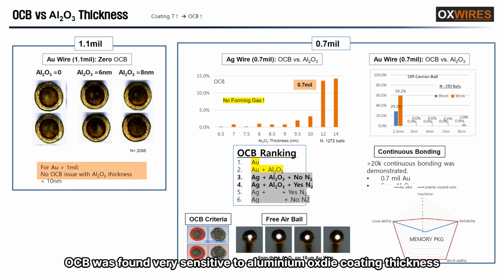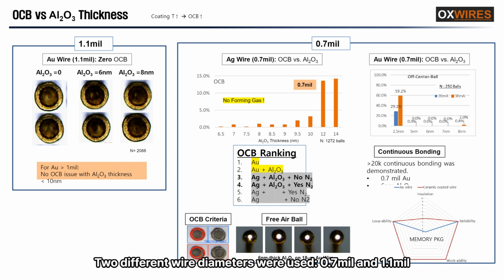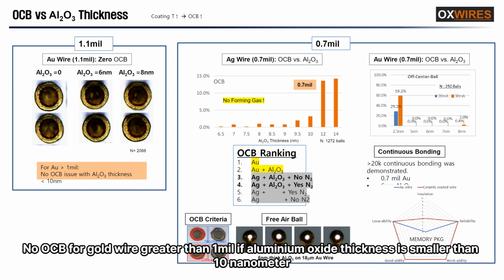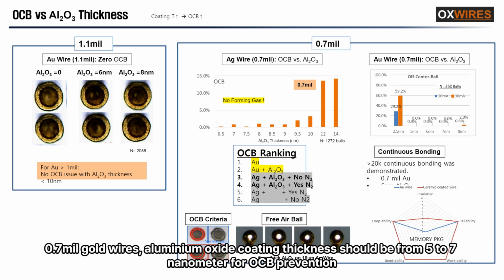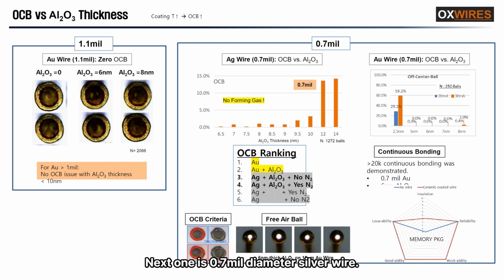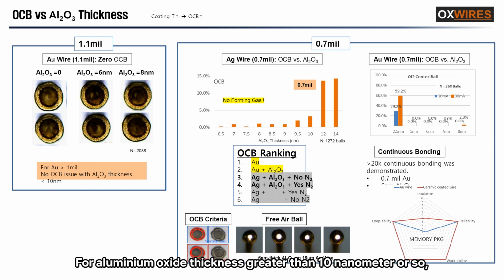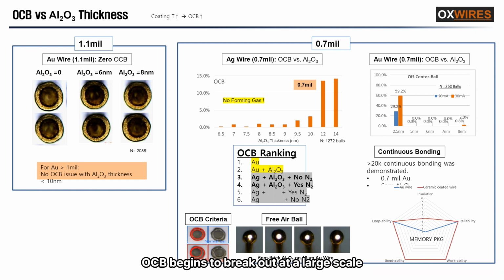OCB was found very sensitive to aluminium oxide coating thickness. Two different wire diameters were used, 0.7 mil and 1.1 mil. Two different wire metals were used, gold and silver. No OCB for gold wire greater than 1 mil if aluminium oxide thickness is smaller than 10 nanometer. For 0.7 mil gold wires, aluminium oxide coating thickness should be 5 to 7 nanometer for OCB prevention. Next one is 0.7 mil wire diameter. For aluminium oxide thickness greater than 10 nanometer or so, OCB begins to break out at a large scale.